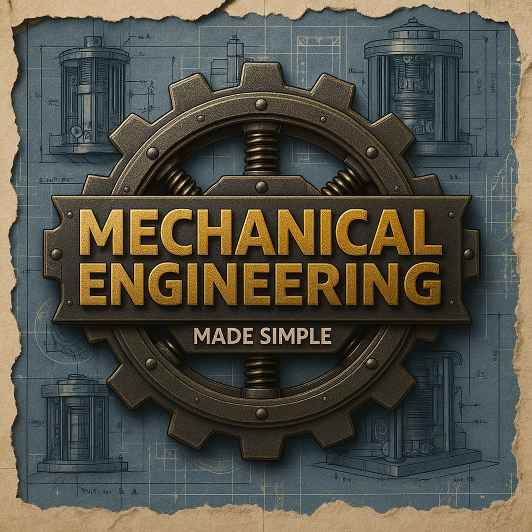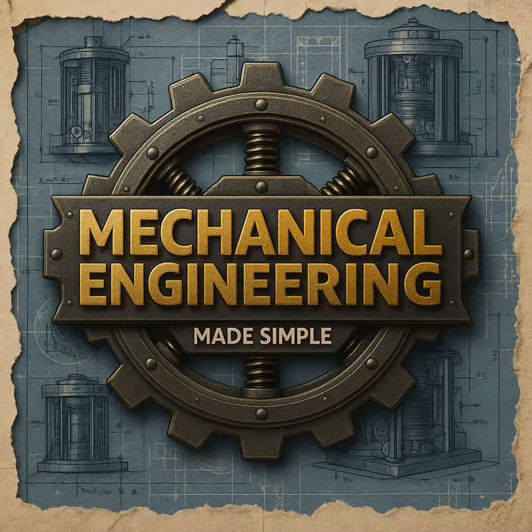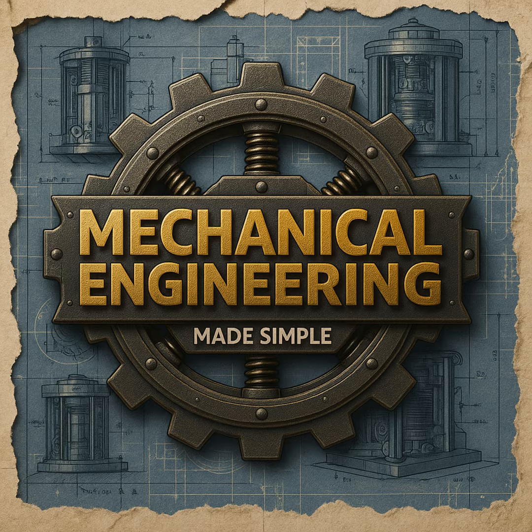Oh, I see where this is going. As it bent the wire, it pressed a tiny microscopic indent, a nick, into the surface of the steel. And because the spring is cycling under heavy load, that tiny nick becomes the focal point for all the stress. It acts as an aggressive stress riser. The bending forces concentrate entirely on that microscopic scratch, initiating a fatigue crack. With every cycle of the spring, the crack propagates deeper until the leg snaps clean off. So easily avoidable, too. Extremely. A designer can prevent this by explicitly specifying generous, controlled bend radii on the engineering drawing, forcing the manufacturer to use properly rounded tooling.